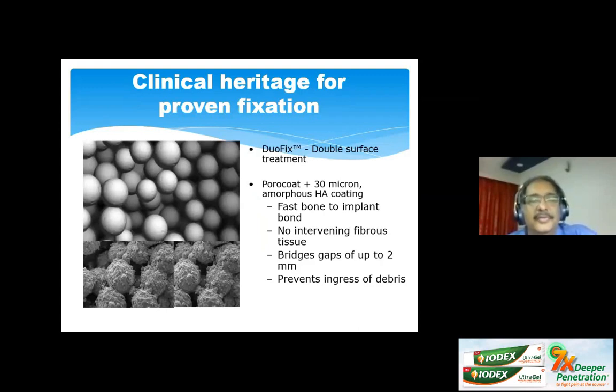Now, all these uncemented sockets are lined by materials which improve integration into bone. They have to, if you understand, do the role of the cement, and they depend on primary stability. If you are not going to depend on your screw fixations for stability, then you're going to have a cup which fails very soon. And Porocoat is the most common material used, which allows the bone to bond to the implant. There should be no intervening fibrous tissue, and it also prevents ingress of debris, thereby the osteolytic potential which can be expected when you're using a polyethylene liner is reduced to a very large extent, though not eliminated.